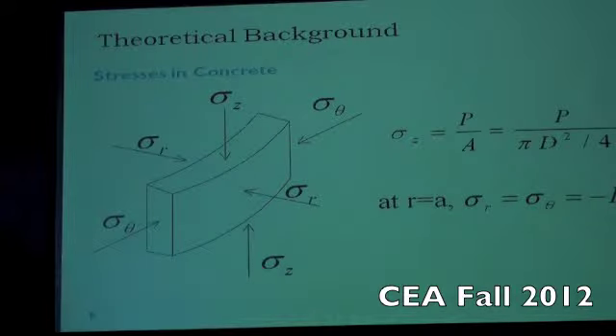First of all, due to the applied axial load, it's subject to normal axial stress, denoted here as sigma z, and sigma z is equal to the applied load divided by the area, which is pi d squared over 4. And then due to the confining effect of the pipe that's surrounding the concrete core, the concrete is triaxially compressed. In the lateral direction, it's subjected to sigma r, which is a radial compression, and sigma theta, which is tangential or hoop compression. At r equals a, at the edge, the radial stress is equivalent to the tangential stress, also equivalent to P naught, which is the pressure applied by the tube on the concrete it is in contact with.